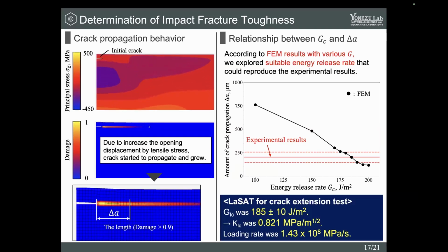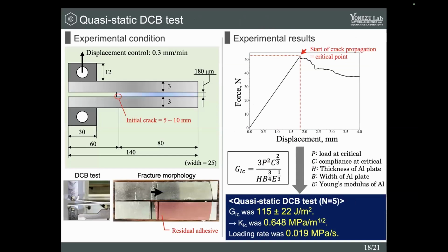This graph is the relationship between energy release rate GC and the amount of crack propagation obtained by FEM. According to this figure, we could determine the impact of fracture toughness as 185 joule per square meter. In addition, we conducted quasi-static DCB tests. This is an example of force displacement curve obtained by DCB test. And using this curve and this equation, we determined G1C was 115 joule per square meter.